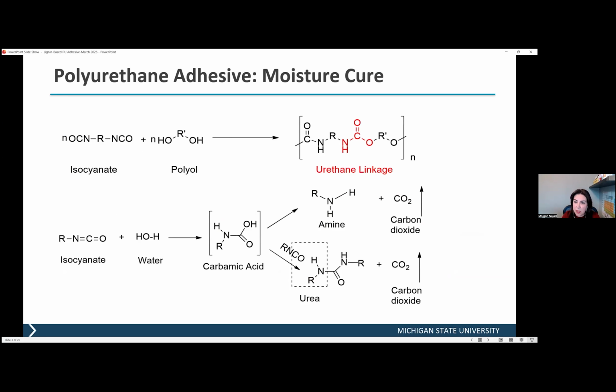Some of you might have heard that when polyurethane adhesives are used in mass timber applications, they usually call it moisture cure. The reason for that comes back to these structures. I mentioned that isocyanate is going to react with polyols to form urethane linkages. But when they apply the adhesive on wood, they usually require some level of moisture in the wood. The excess isocyanate also reacts with the moisture in the wood, forming an unstable carbamic acid that either cures to amide groups with CO2 released, or creates urethane linkages and then CO2.